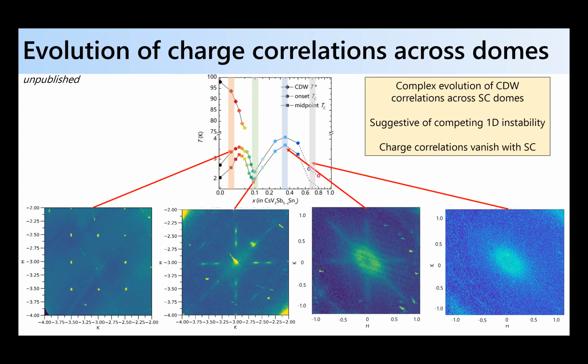Yeah, so people have applied, this is what's weird. Naively you would apply in-plane strain and you would think that the CDW temperature would shift, TC would shift, and that effect seems to be reasonably weak. It's mainly driven, in fact, via the Poisson ratio; it's the C-axis response that really drives down the CDW. People haven't done hydrostatic strain. People have done hydrostatic pressure, and basically the CDW collapses quickly, and eventually another superconducting phase forms. But at that point, the C-axis has collapsed by 20%, something like this. So it's very anisotropic.